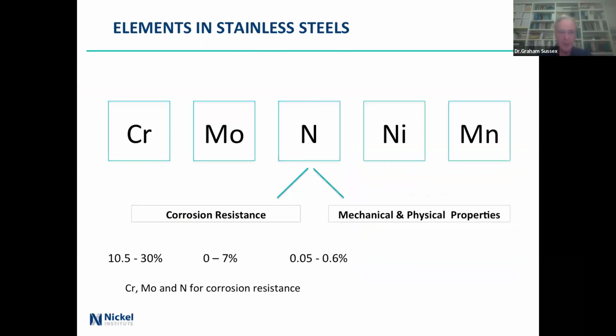And what's in it? Chrome, moly, nitrogen, those give you corrosion resistance, and the nitrogen, nickel, and manganese give you your physical and mechanical properties. The amount of material that's in there, manganese I've put up to 11. That's only in some of the specials where you've really got to work at getting nitrogen in, because manganese does make it a bit easier.